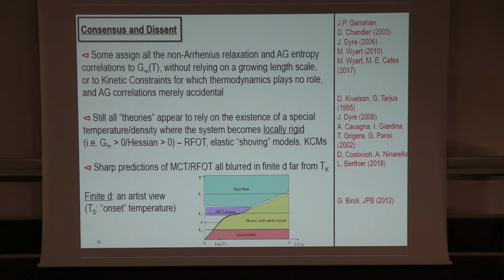Still, it seems that all the theories, even the ones that are far from RFOT in spirit, appear to rely on the existence of a special temperature or a special density where the system becomes locally rigid, where this idea of free flow, unencumbered, to something that is costly to move, seems in all these theories to happen at some well-defined temperature.